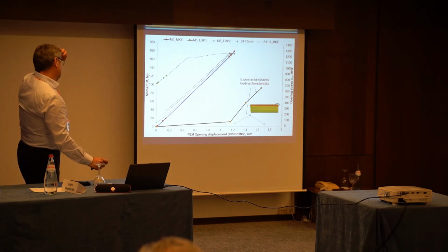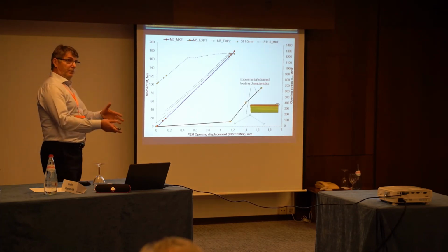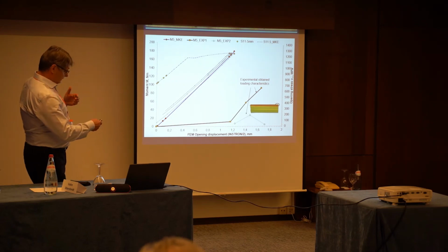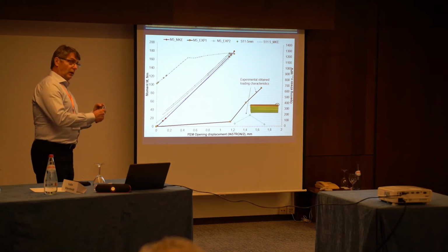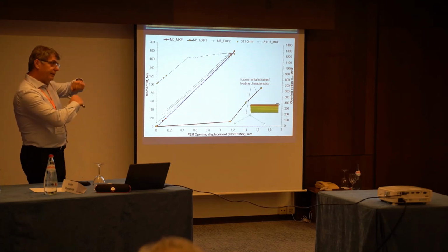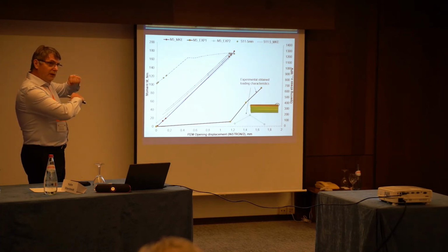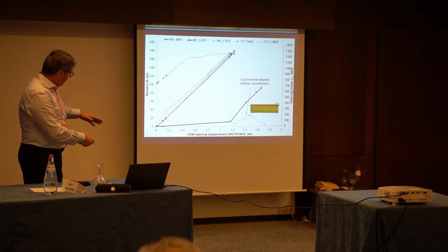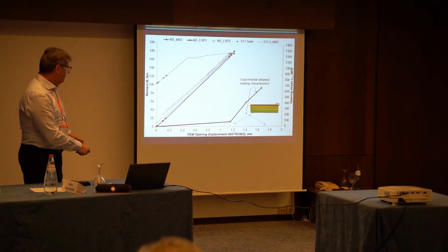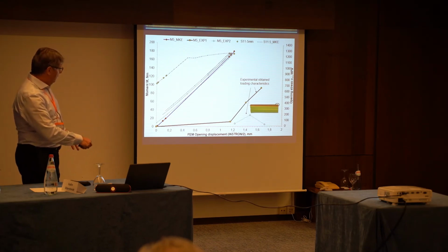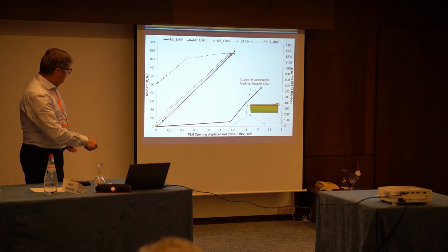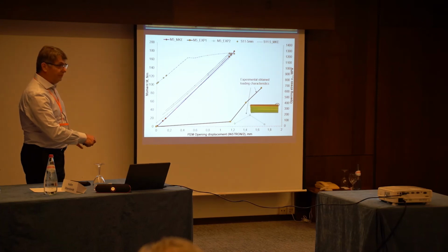Then the second thing is, now we want to combine with experiment. Why? Because first we have this movement here at this point. What is this actually? This has happened because you have some clearance, some imperfection at the start of loading, and then when we start with this, let's say, small load here, you go to this linear. This linear should be the same for loading with respect to the moment. So this will be your load, it should be the same line, let's say starting from here up.